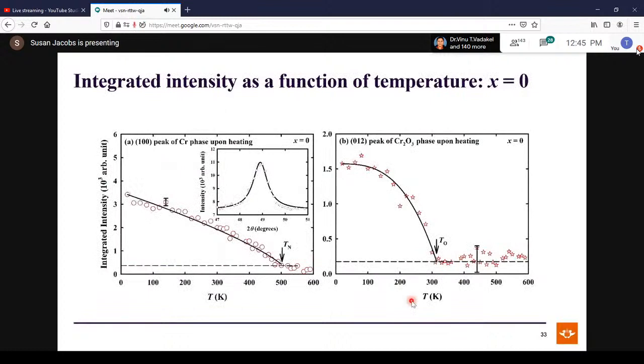Okay, and from neutron diffraction, you can also determine Tn. So you have your magnetic peak, which you saw, and the area below that peak is what we call the integrated intensity. So how do we determine Tn? Well, you have to fit a curve on that peak, find the area below the peak, and where that area goes to 0. So when the peak disappears, then that is your transition. Which means the area should go to 0. So the temperature at which the integrated intensity goes to 0, that is your Tn.